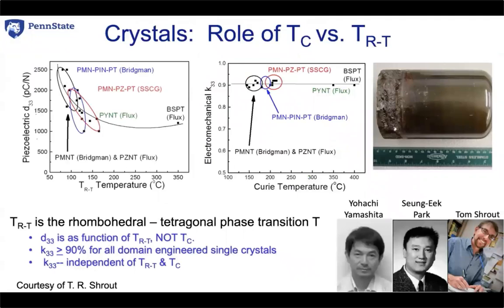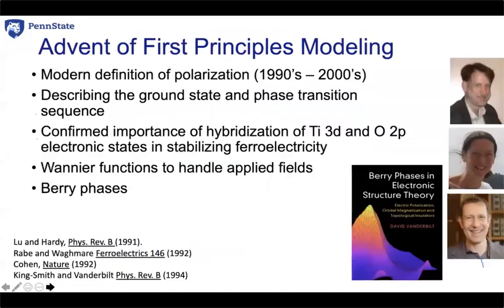I show pictures of three of the key contributors to this field here, but among the things that's been very, very interesting has been to watch the evolution of crystal growth methods for these complex compositions, to watch the evolution of the understanding that it's really the low-lying phase transformation temperature, the rhombohedral to tetragonal temperature, rather than the Curie temperature that governs the utility of and the useful temperature range of these materials.